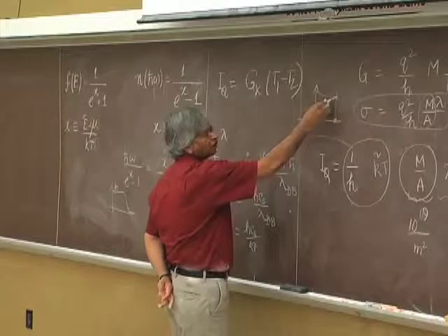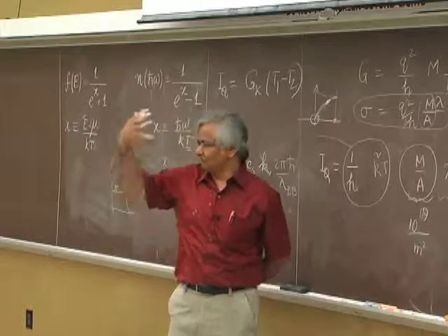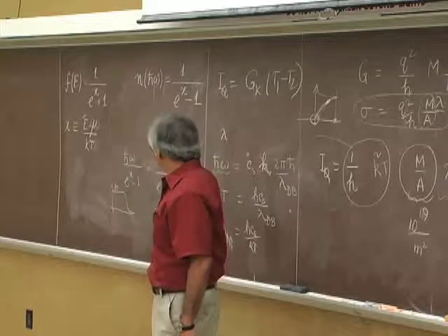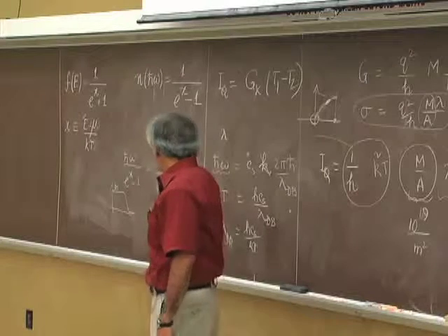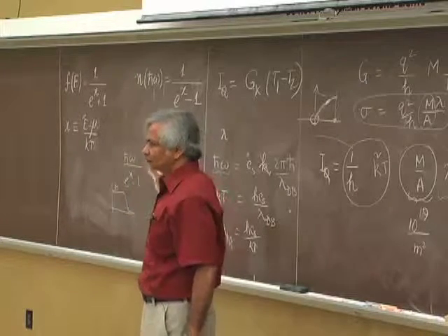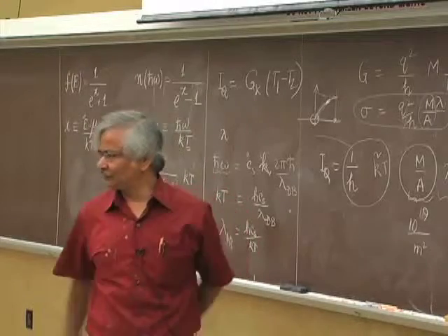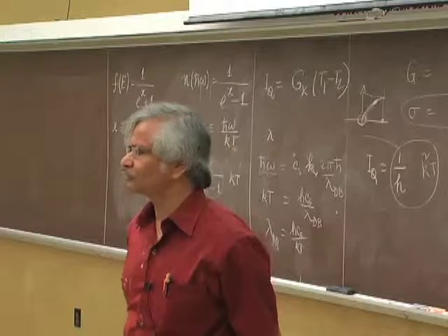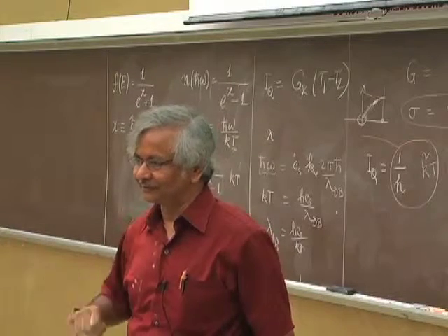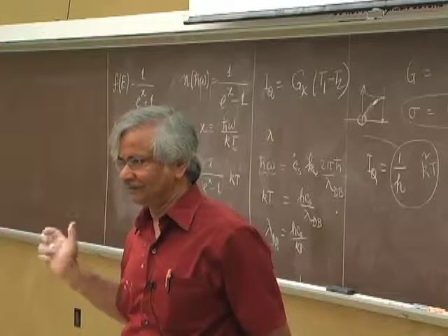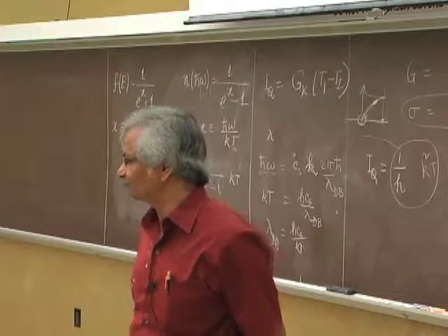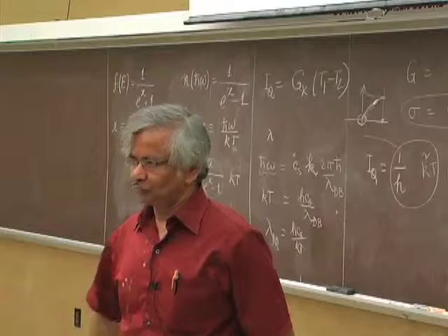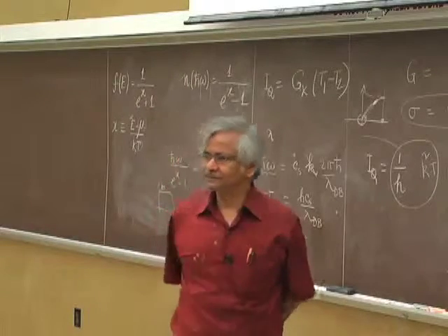A lot of these, because there's a lot more modes, the density of modes goes up in energy also. But then it gets cut out by that function, the e to the power, the Bose function. But that's why I said kT may be a good number to go with, but it could be less than kT. All that needs careful discussion though. But the thing that is different I notice is that while with electrical conduction there is this orders of magnitude difference between a metal and an insulator, there is no such comparable thing here, which is why thermal conductivities don't really differ by major orders of magnitude. It is within a relatively small window really. That's what I've seen so far.